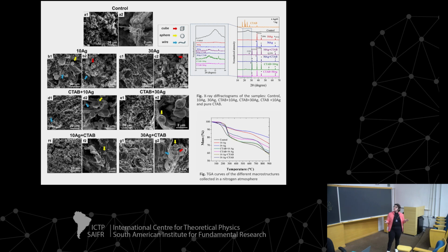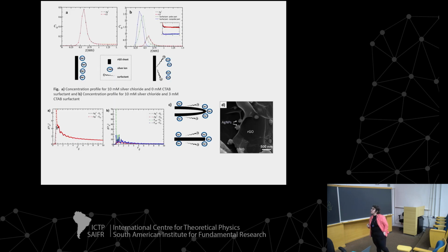We have different kinds of materials with nanoparticles up to microparticles, whites, cubes. Some materials present cubes. Some materials present spherical nanoparticles. All these materials present high thermal stability. Again, these nanoparticles are mainly pure silver nanoparticles and silver oxide core-shell nanoparticles. But we need to understand why some of these materials present this kind of structure where the nanoparticles are in the wrinkles, mainly in the wrinkles. Why? So Bordin did some calculations that help us to understand when we add firstly a surfactant molecule.